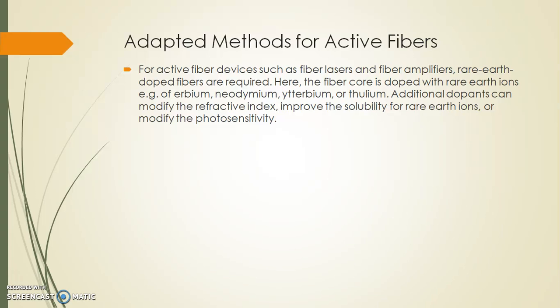Another common technique is solution doping, where initially a porous silica layer, not yet containing rare earth ions, is deposited on the inner side of a hollow silica tube. This layer is then soaked with a solution containing a rare earth salt. Later on, the preform needs to be further processed to form a dry and compact rare earth oxide layer. An alternative technique is direct nanoparticle deposition from some aerosol. This method allows for high doping concentrations with good homogeneity and accurate control of the doping profile.